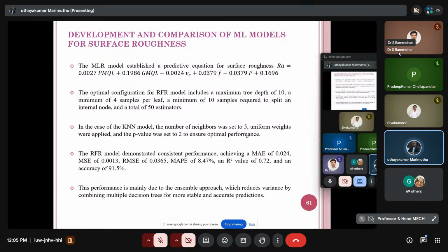The MLR model established a predictive equation for surface roughness. The R value is listed here. The optimal settings are 4 samples per leaf, a minimum of 10 samples required to split an internal node, and a total of 50 estimators. For the KNN model, the number of neighbors was set to 5, uniform weights were applied, and the p-value was set to ensure optimal performance. The RFR model demonstrated good performance, and it is presented here.